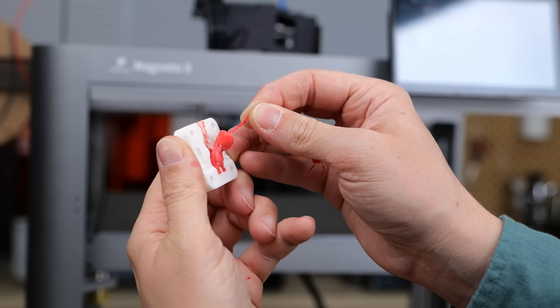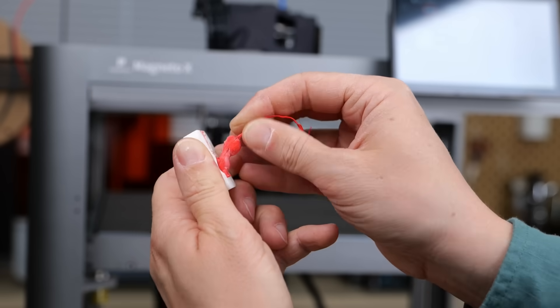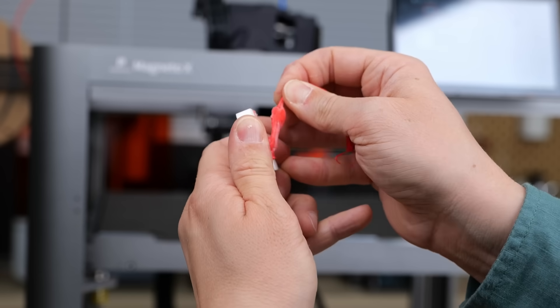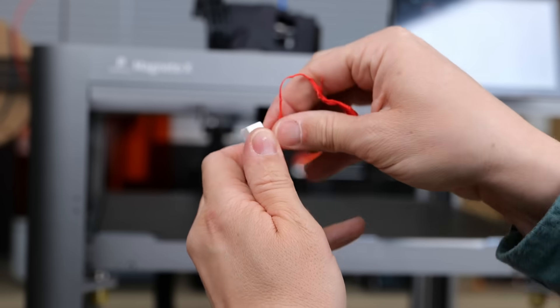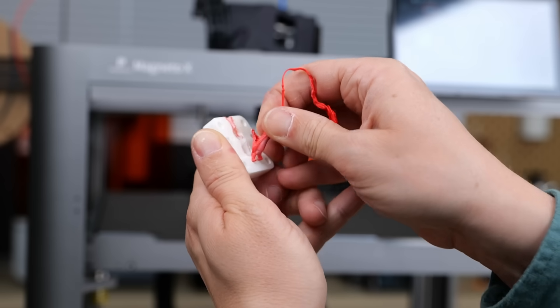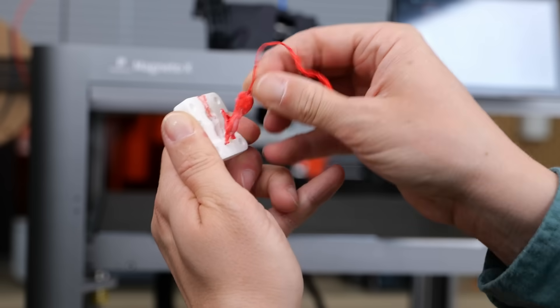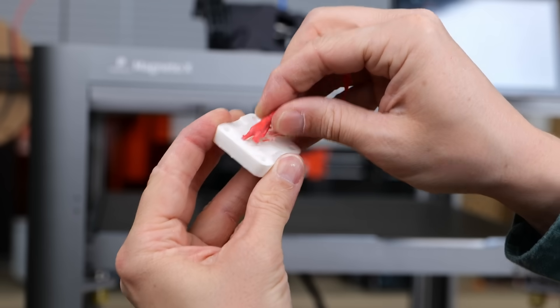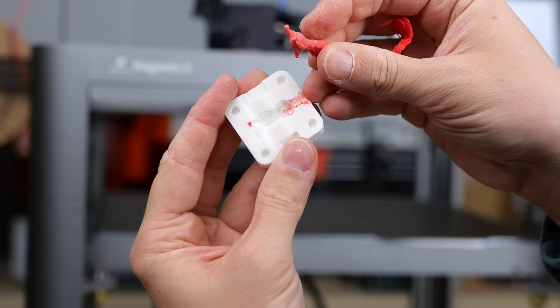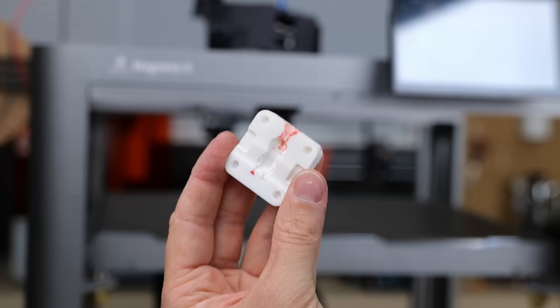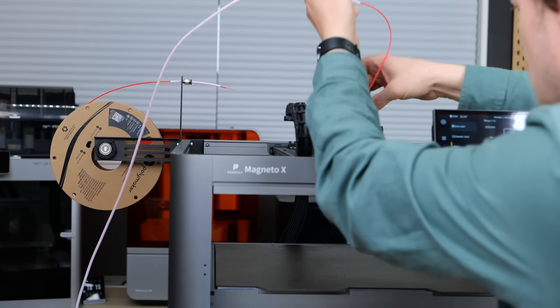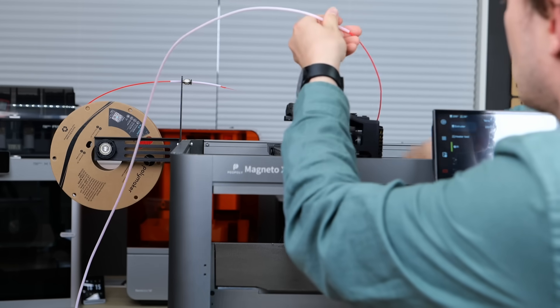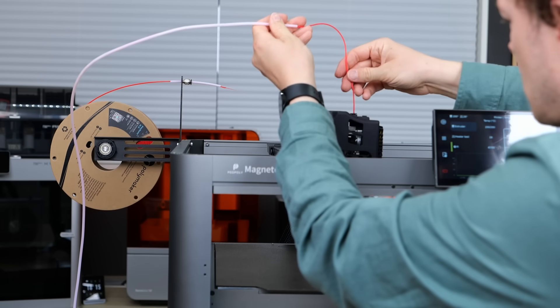I was a bit impatient and demolded the part a little early which not only deformed it because it still was a bit soft but also showed me that my almost no undercuts model still had some undercuts and I was sure that it would have been a pain or even impossible to demold a fully solidified part in PLA. That's why I switched over to the material I anyways wanted to use for my Mini Me which was flexible TPU.